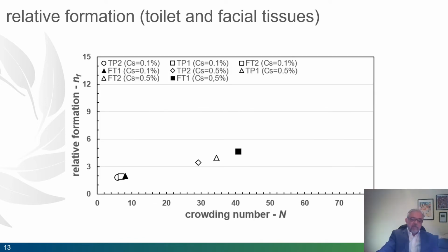The next two slides display the results of relative formation computed for traditional tissue paper compositions, also for the range of stock consistency from 0.1% to 0.5%. As mentioned before, lower NF denotes better formation uniformity or lower grammage distribution variance. Looking at the results for toilet paper and facial tissue furnishes, we see that the lowest relative formation was found for the 100% hardwood or eucalyptus furnish, like in toilet paper. The combination of length and coarseness of eucalyptus fiber is what produces the lowest crowding number.